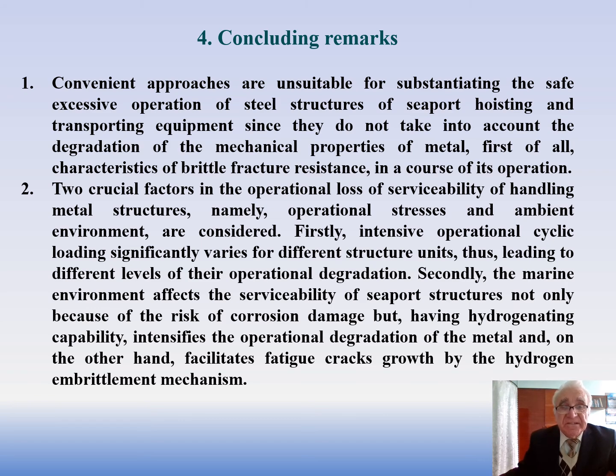Two crucial factors in the operational loss of serviceability of handling metal structures, namely operational stresses and ambient environment, are considered. Firstly, intensive operational cyclic loading significantly varies for different structure units, thus leading to different levels of their operational degradation. And secondly, the marine environment affects the serviceability of seaport structures not only because of the risk of corrosion damage, but having hydrogenation capability intensifies the operational degradation of the metal and, on the other hand, facilitates fatigue crack growth by the hydrogen embrittlement mechanism.